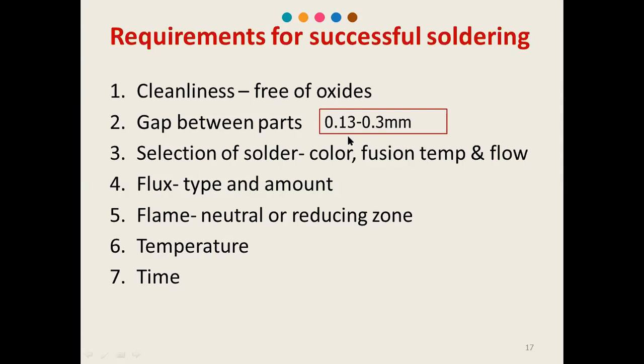Now next, selection of the solder. We have seen the ideal requirements, how your solder should be: the color, the fusion temperature, the flow, the strength, everything you should see. Then the flux type and the amount. You will have to see which type of parent metal it is, whether it is a noble or a base metal. Accordingly, you will have to use a gold solder or a silver solder. Now the flame: you will have to use the neutral or the reducing zone. Either you should use propane or butane. Then the temperature used during the soldering or brazing procedure should be the minimum that is required to complete the brazing operation.